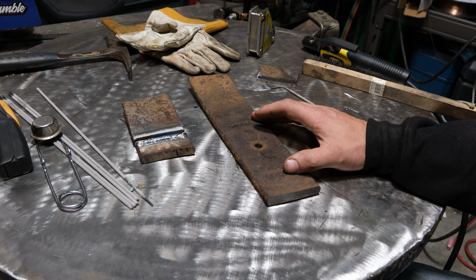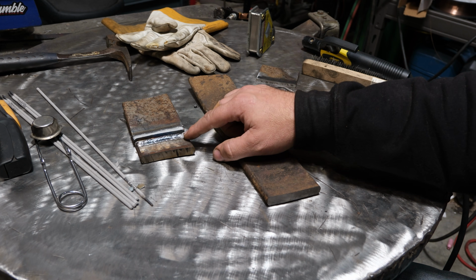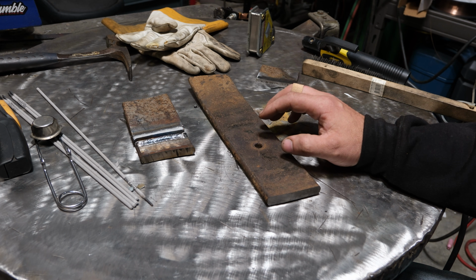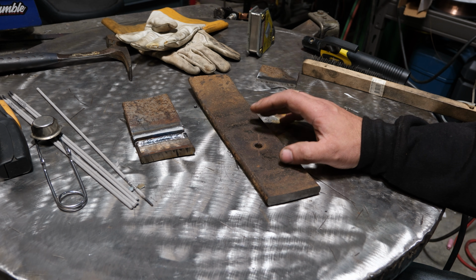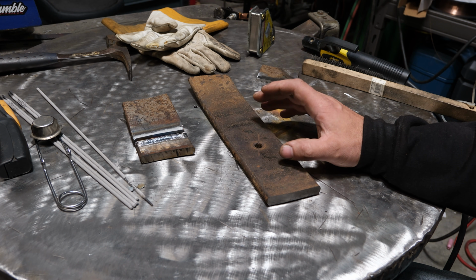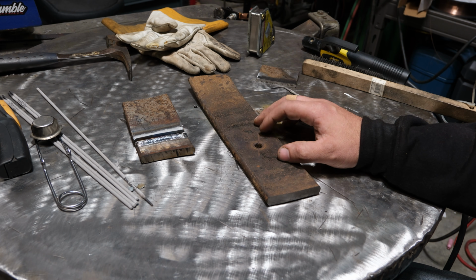Normally, I would do this type of repair with a 312 stainless-based rod. And just like you saw in this 7018, the weld isn't cracked by any means, and the weld isn't what failed. More or less, that base material had more to do with the failure.